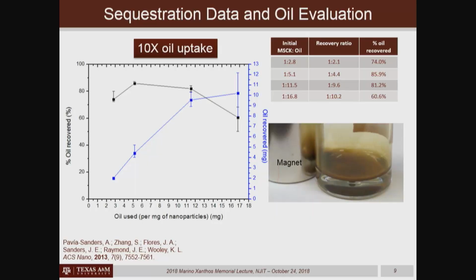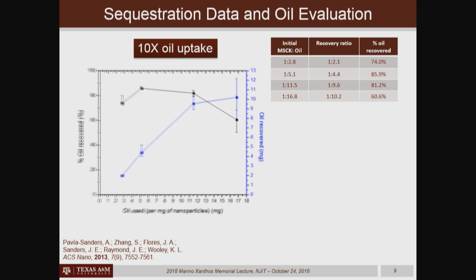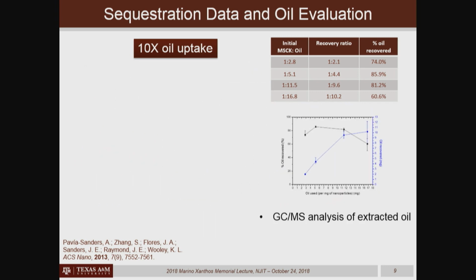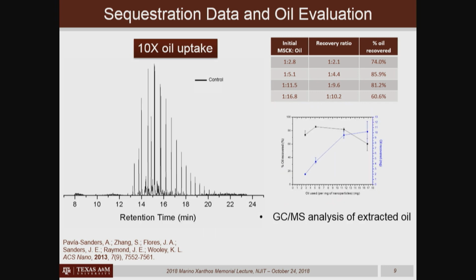What we also found is that when she went to really high loadings of crude oil relative to particles, the system got to the point where this oil could be removed by a pump, for instance. It's no longer just a sheen on the surface of the water. And what was also found was that the crude oil that we were working with, even though it had been weathered, was still a complex mixture of hydrocarbons.